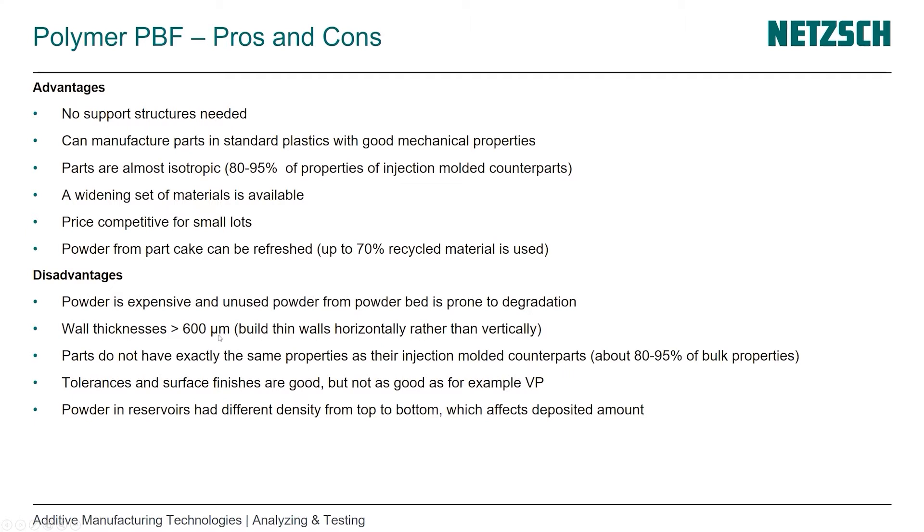Walls should be built horizontally rather than vertically because of step structures that we get in there. Parts do not have exactly the same properties as the injection molded counterparts, so we're not there yet.